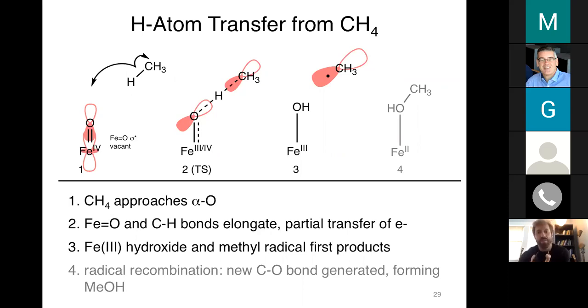So what happens is, as you move from the ground state, which is labeled 1 in this scheme, to the transition state, which is labeled 2, the CH bond and the iron-O bond are each going to elongate. And as the iron-O bond elongates, that frontier molecular orbital is going to be stabilized, so it's going to be lower in energy. And as the CH bond elongates, the CH sigma bonding orbital is going to be destabilized. So these structural changes bring the CH sigma bond and the iron-O sigma star levels closer in energy. And then at the transition state, you have very nice energy match and orbital overlap between the CH sigma bond and the iron-O sigma star level.